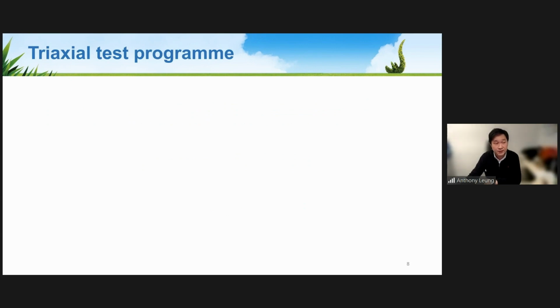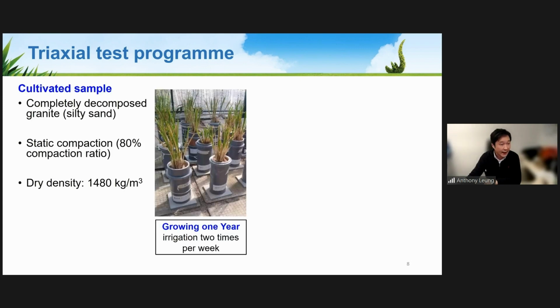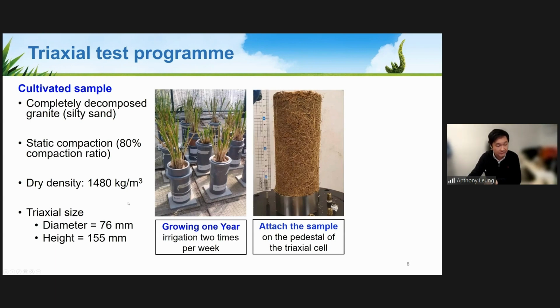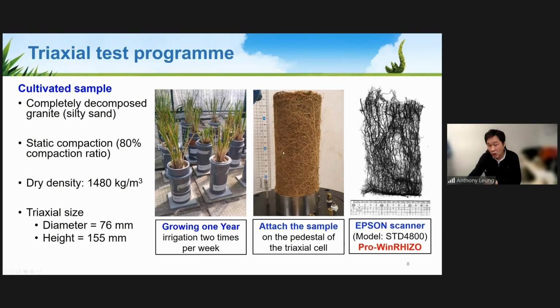So we use the triaxial testing system available at the Hong Kong University of Science and Technology. And the soil we use is the local soil called completely decomposed granite, which basically is silty sand. And we compact the soil to a degree of compaction of 80%, achieving this dry density, which is suitable for plant growth in the urban area. So this is the dimension of the triaxial samples we have been using. After testing, we open up the samples to look at the root distribution using a scanner so that we can better inform our modeling in the later part.